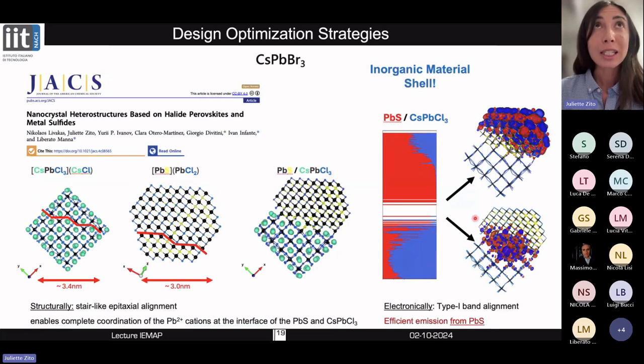But more recently, in the context of the IEMAP project, we are investigating another type of strategy to passivate these surface defects, which is to interface our material, in this case the perovskite, with another inorganic material. As Toso also anticipated, we have investigated how to interface a chloride-based perovskite with lead sulfide. And in the experiments, they found out that these systems have a heterodimer structure, represented here.